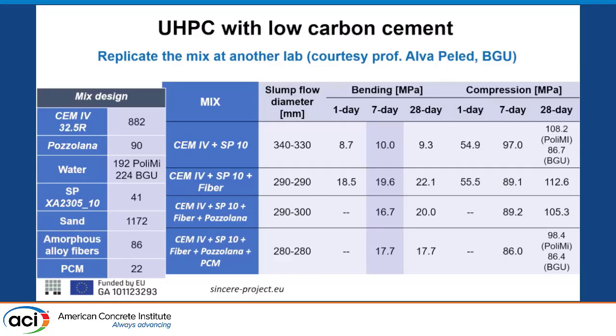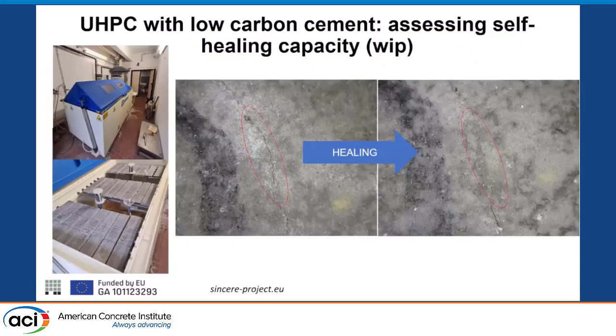What was the other outreach? We tested this material in different universities. Same recipe, same supplier of material, but different labs. And you can see that, for example, in Ben Gurion University, they made the same material to use with textile reinforced concrete application. They just had to adjust the water, but we got very similar performance. So this shows that no matter where you produce this material, you can get similar performance. And this is also good from the point of view of sustainable UHPC application. It's not a proprietary mix composition. It's something that you can reproduce with locally available constituents almost everywhere.